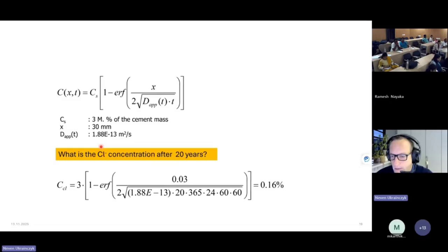So if we plug in the values, we get that the chloride content at the depth of the steel bar is 0.16% after 20 years. Sorry, this is not the critical content, this is the predicted chloride content, 0.16%, and the critical amount is 0.4% per mass of cement. So it's less than 0.4, then we are good. So this structure will last at least for 20 years.